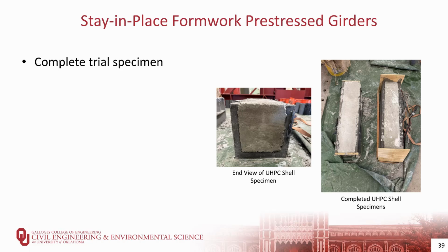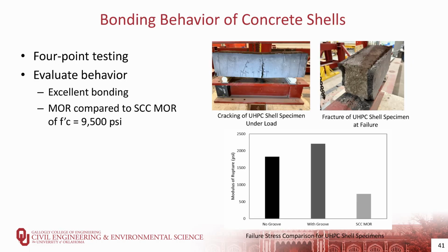And so when we went to the finished specimen, you can see that interface around the shell. But when we did the testing, we didn't see any movement between those individual materials. Now, for the hybrid specimens that we've constructed up to this point, those were a vertical interface rather than a horizontal interface, and those were cast with both concretes being fresh.